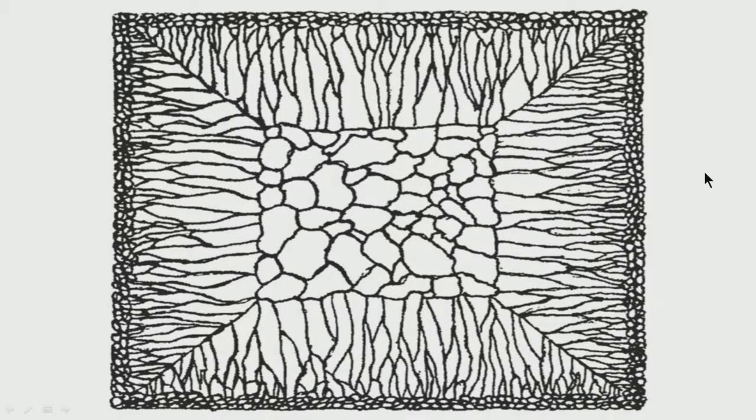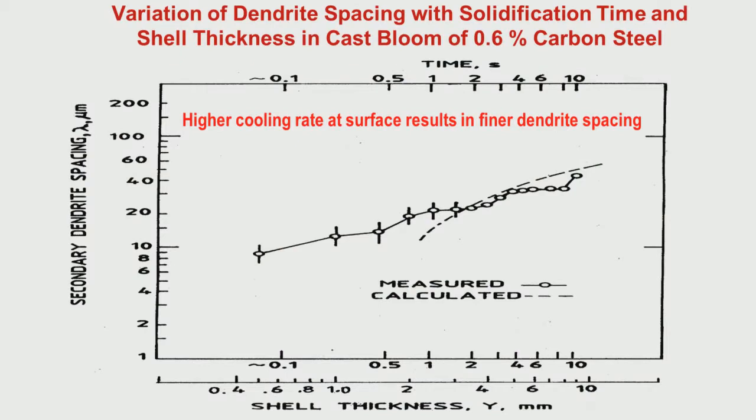This facility is not very expensive. Many casters, billet and bloom casters have this facility, where even at slightly higher superheat, maybe at 20-25 degree, you can have maybe say 30% equiax zone, 30-35% equiax. So, lower superheat and electromagnetic stirring, these two are useful for getting good solidification structure. This I had mentioned earlier, that how the rate of cooling determines the dendrite size.